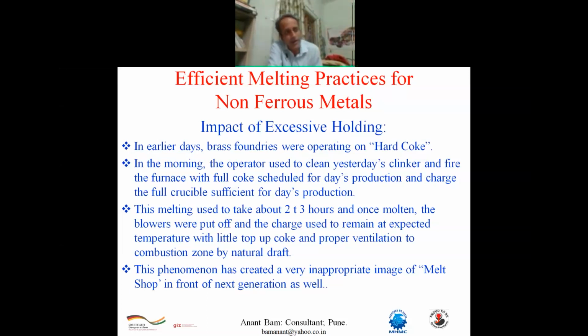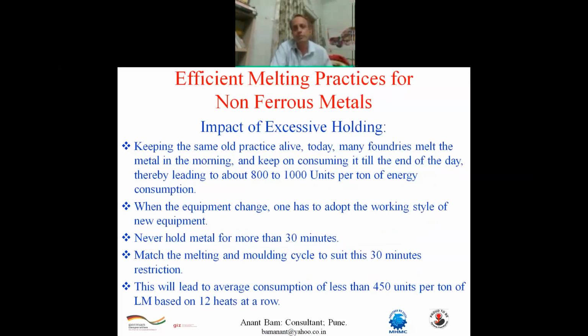So that practice of charging the furnace in the morning and utilizing the full fuel gradually over 6 to 8 hours, that leads to full day production for those people. That habit became a culture of such foundries. And that culture never changed with the change of equipment. The old coke-fired crucible pit furnace got replaced by induction furnace. But the habit of keeping the 300 kg liquid pool available from morning till evening, it never changed.